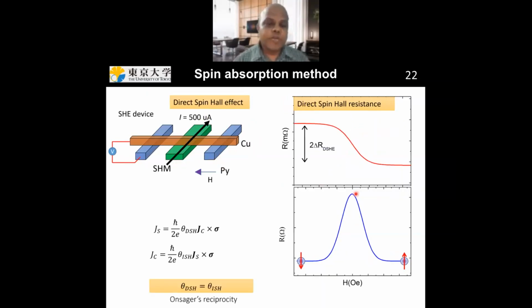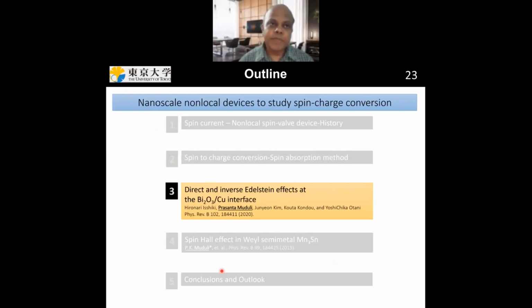So in the same device you can also measure the direct spin Hall effect. In this case, what you have to do is pass charge current in the spin Hall material, and you create a spin accumulation, which you can detect non-locally by putting a voltmeter between this ferromagnet and the copper. So in this case also you can get a signal something like this, and you can measure the direct spin Hall effect. Usually what we see is that due to Onsager reciprocity, the spin Hall angles measured in both methods are equal to each other.